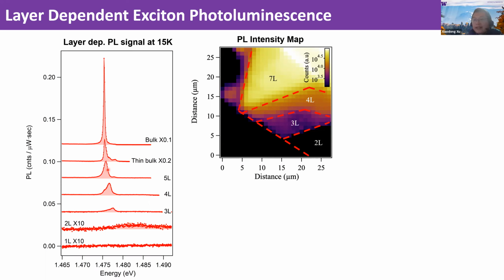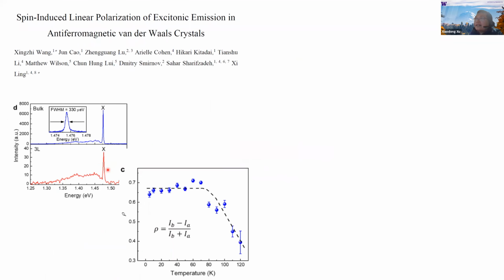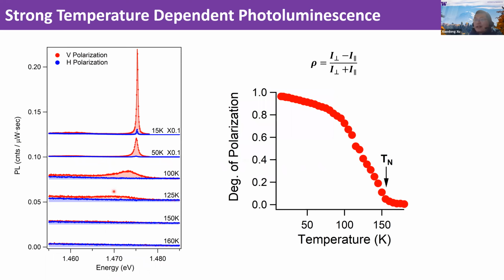So here's the general feature I can argue, right? The linewidth of the exciton represents how noisy your environment is, basically the dephasing. This represents the T2 of the excitons. Then I would argue that when you form these zigzag antiferromagnetic orders, the spin is sort of pinned, and then maybe that reduces the fluctuations. That's why the width is narrow. But you can see that when I increase the temperature, and that's another plot I have here, the width actually increased dramatically. Of course, I cannot say my width is mainly contributed from the spin fluctuations, because the phonon also contributes to the width. So I cannot say anything conclusive, but at least this gives us an indication. The width might represent some spin fluctuations.